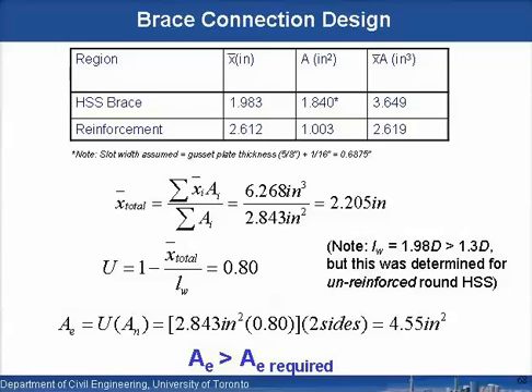So we will still stick with this shear lag reduction factor here, which is a slightly safer approach of using 0.8. So we apply the 0.8 reduction factor to our area that we've calculated up here, and then we've got this area of the tube on two sides of the gusset plate, so we double it up and we get an effective area of 4.55 square inches at the critical location, which is more than the effective area that we required. So that's fine. We will not have this circumferential fracture phenomenon due to shear lag occurring.